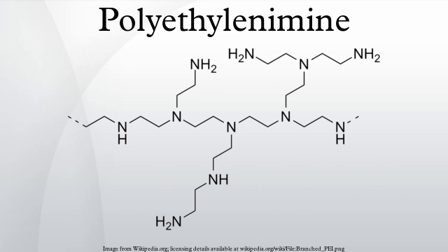Amino groups incorporated by both paths have shown synergic effects, achieving high CO2 uptakes of up to 235 mg CO2 per gram. CO2 adsorption kinetics were also studied for these materials, showing similar adsorption rates to impregnated solids. This is an interesting finding, taking into account the smaller pore volume available in double functionalized materials. Thus, it can also be concluded that their higher CO2 uptake and efficiency compared to impregnated solids can be ascribed to a synergic effect of the amino groups incorporated by two methods rather than to faster adsorption kinetics.